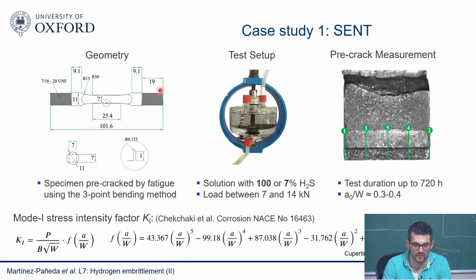So you have a plate like this. You induce a crack here. You do some sort of fatigue pre-cracking. And then you basically introduce a solution with various amounts of H2S. You hold your load constant, and you wait. And the standard tells you that you need to wait for 720 hours.